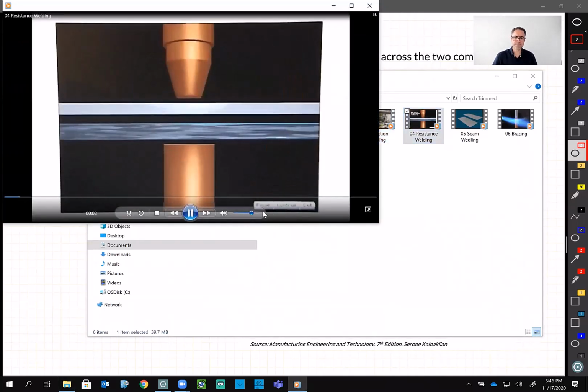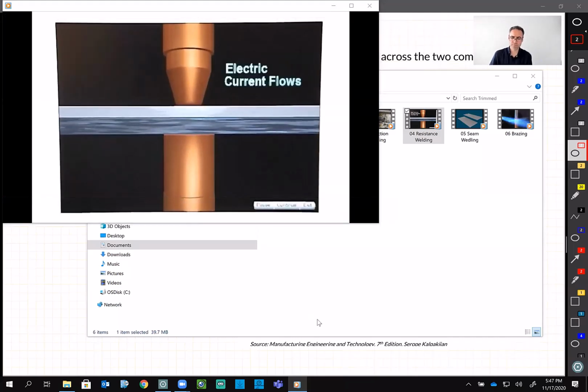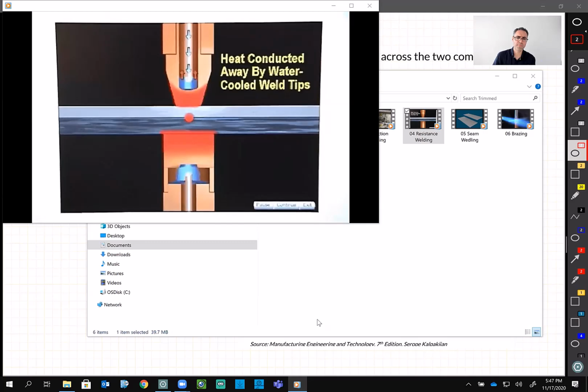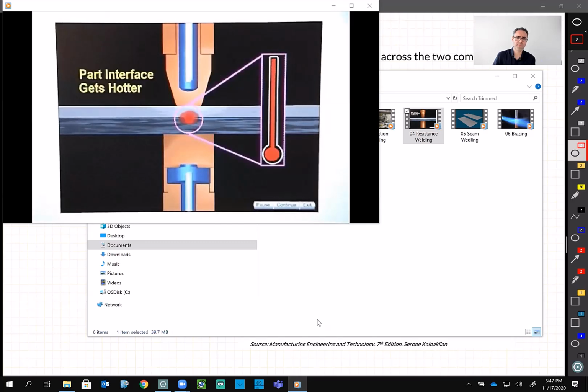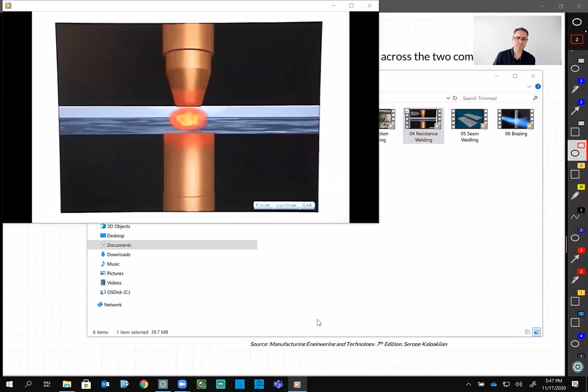Resistance welding is a process where metal parts are squeezed between two weld tips. Current flows between the weld tips and encounters resistance at the weld tip interface and at the part interface. Resistance to the current at the part interface creates enough heat to melt the metal and cause a weld nugget to form. The heat at the weld tip interface is conducted away by the water-cooled weld tips while the part interface continues to get hotter and hotter. About halfway through the weld time, the metal at the part interface begins to melt, then a weld nugget is formed. When the weld time is complete, the current stops flowing. Then a hold time of approximately 4 to 5 cycles is used to give the weld tips enough time to absorb heat from the outer perimeter of the weld nugget and cause it to harden before the weld tips open.